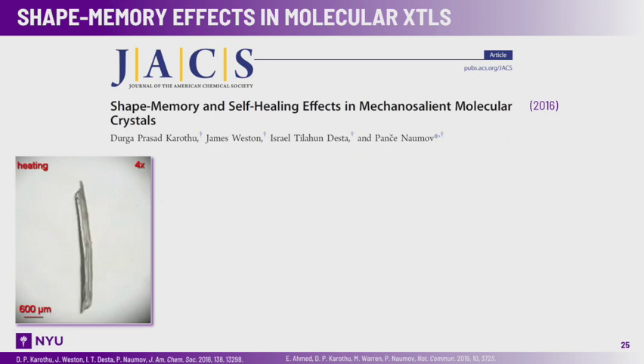Also, one of our discoveries back in 2016, it was a really good year for us, we found a shape memory effect in an organic crystal. What you see here in the movie is a crystal which has been subjected to mechanical force, it deforms, and then after you heat it, it goes back to the straight shape. And then you can go back and forth, similar to what you would see with a shape memory alloy, but in this case, it's a simple organic crystal.